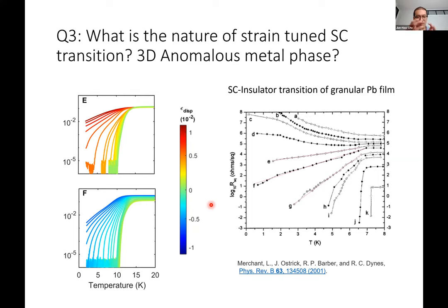So obviously a deformation of the electronic system will couple to the omega zero B2g phonon modes, which is basically an anisotropic strain. Now, the question is, if you really turn off this coupling, or somehow you have a fictitious system where you fix the strain to be zero so that the system doesn't move, does the electronic system still spontaneously try to form an anisotropic strain? If it still does want to do that, then I will consider it as an electronic nematic phase. And the iron-based superconductor is one of them, where you can measure this by doing elasticity measurements, where you measure the response of the electronic anisotropy at a fixed strain, and they're still showing divergent behavior. So that's how I would define electronic nematicity.